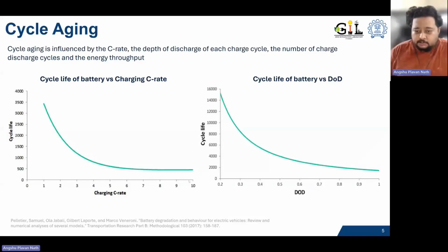Similarly, a similar relationship is seen between your cycle life and your depth of discharge. If we do deep swings, let's say 90% swings, where your battery goes from 100% to 10% and from 10% back to 100%, these are deep cycles. Again, your battery deteriorates exponentially quicker compared to if we had smaller depth of discharge cycles.